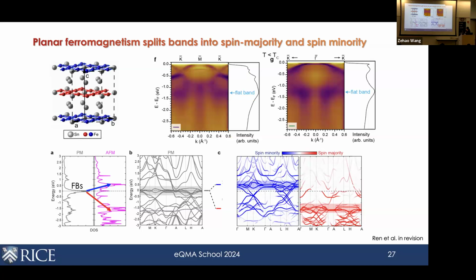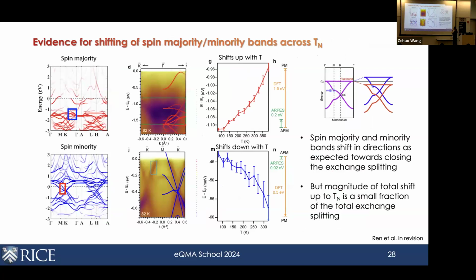Okay, so what do we see? When we measure the band dispersions along some high symmetry directions in the Brillouin zone, we can identify this peak between 1 and 1.5 eV below the Fermi level, which corresponds to the spin majority flat band states. Furthermore, we can track these band dispersions as a function of temperature, and we find that there are regions in momentum space where we can capture bands whose behavior with temperature corresponds to that of the spin majority states. By that I mean when you raise the temperature, they move up. Whereas there are other regions with states compatible with the expected behavior of the spin minority states, and as a function of temperature, they come down.